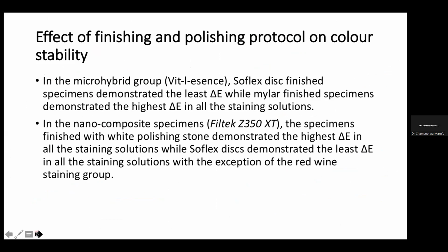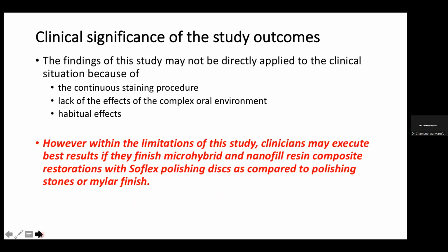And then in the nanocomposite specimen, the specimens finished with white polishing stone demonstrated the highest color change in all the staining solutions, whilst the Soflex disc demonstrated the least color change in all staining solutions, with the exception of the red wine group, which I showed you earlier.